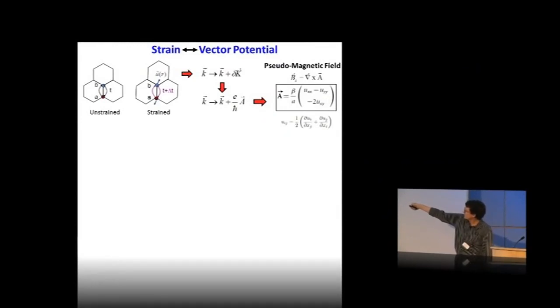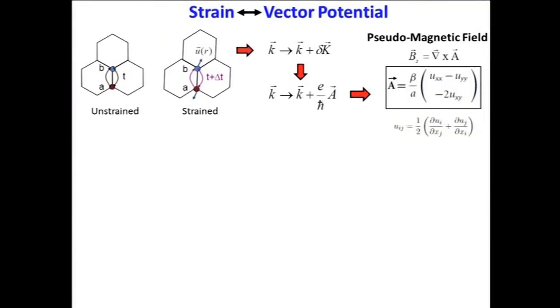And you can see that the pseudo vector potential depends on the uniaxial strain or the normal strain components as well as the shear strain in this way. You can then take the curl of this pseudo vector potential, and that will create a pseudo magnetic field. And so the electrons will then feel that pseudo magnetic field, which arises purely due to strain, even in the absence of an actual magnetic field.